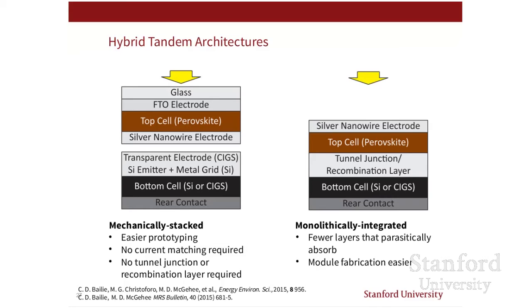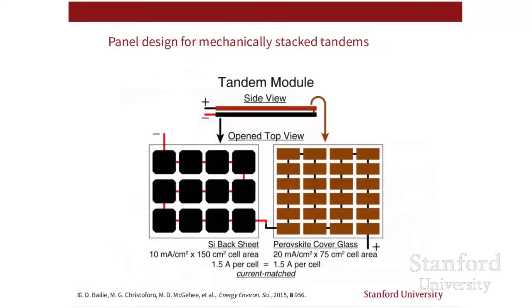And there's some engineering that has to be done to make the right interfaces between the two. With the mechanically stacked tandem, you don't have to perfectly current match. On the next slide, I'll show you can still wire them up in series with each other. You can have a string of silicon in series with a string of perovskite cells, and you can simply adjust the areas in order to get current matching. And if you do that, your panel will still only have two wires coming out of it.